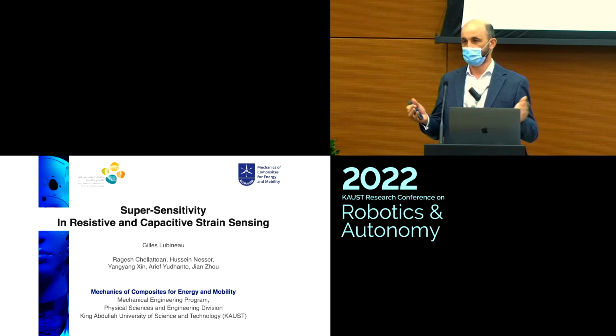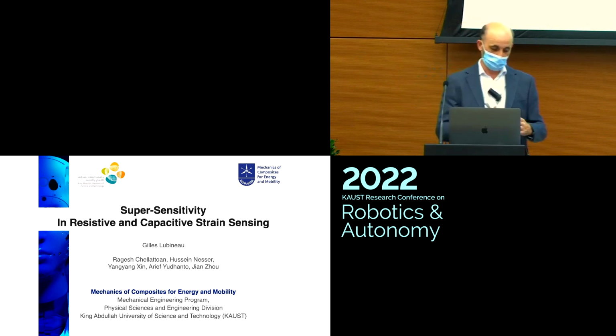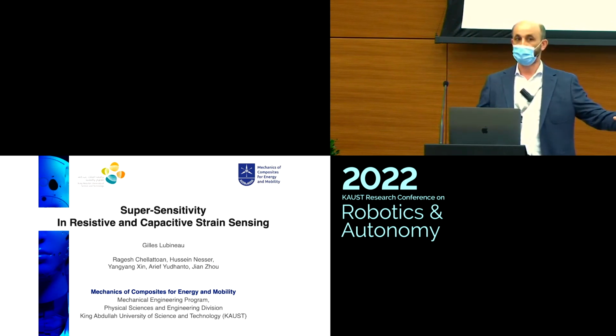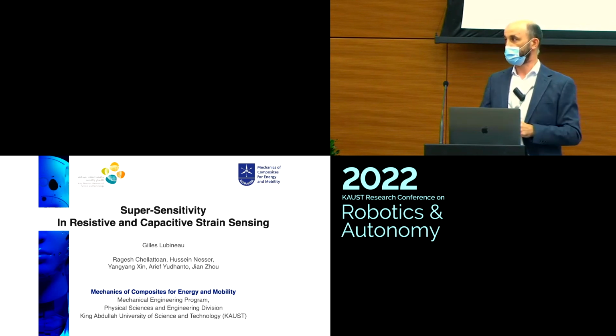This is going to increase so quickly that you cannot monitor 10%, 20% of strain. Very quickly, you will go to a perfectly insulating system. So what is important is to make sure that you have something that can relatively progressively lose the conductivity from 0 strain up to 100% strain. That is a little bit more complicated to do. So that is why we are using CNT paper in this application.